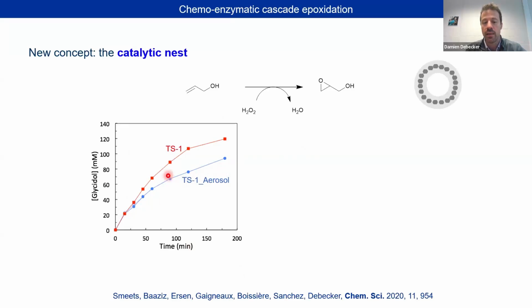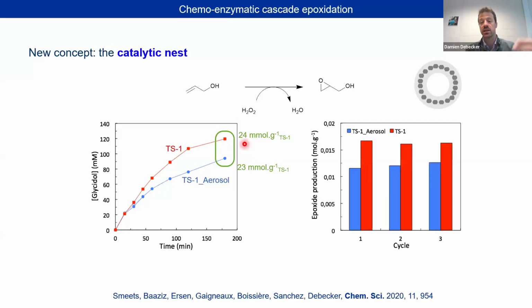You see here the blue line is almost as high as the red line, which is the pristine zeolite. Why is it a little bit lower? Well, because you put a little bit of silica in this material. Silica is not active. So if you normalize by the TS-1, you have exactly the same activity. Also, the catalyst is fully recyclable. So nice. Our nest is okay.